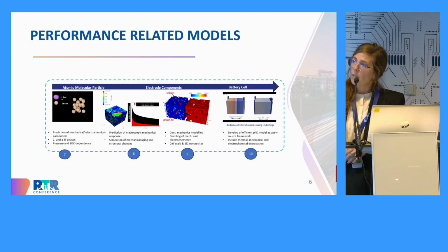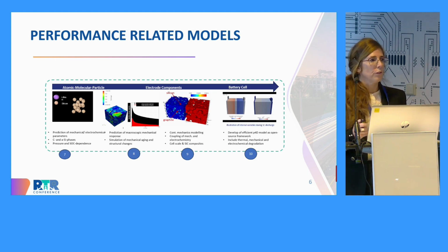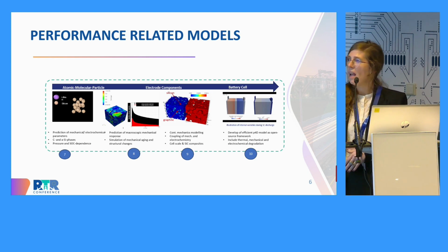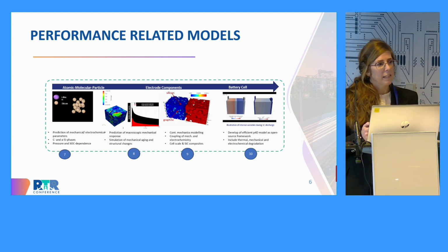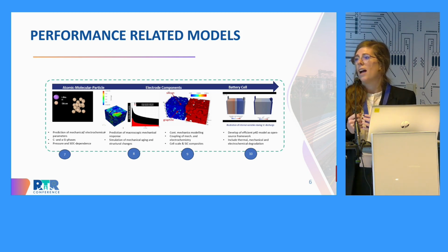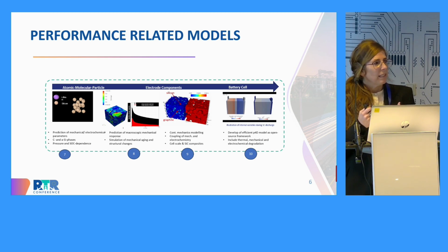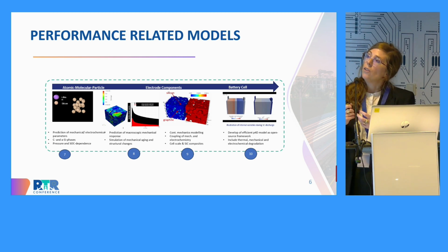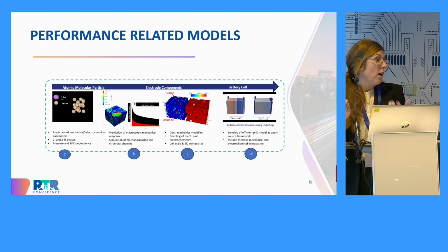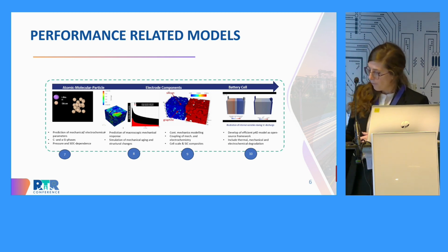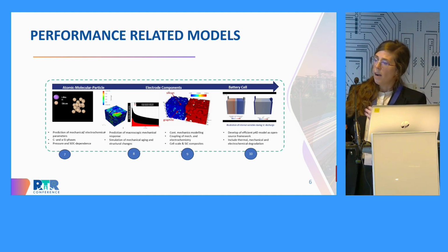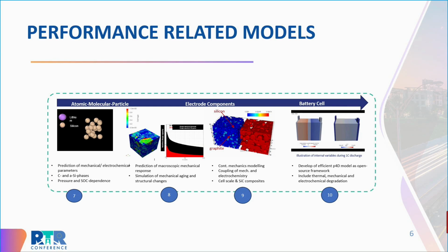So, and then now dealing with the performance, again with this multi-scale approach, we go from atomistic to meso to the continuous scale. And in particular in DEFACTO, we have this graphite silicon, and here it's really important to address correctly the swelling of the silicon, because otherwise it might cause certain cracking. And then this cracking will lead to higher polarizations, and also lower cycle life. So basically, from this multi-scale approach, we predict on the atomistic scale certain properties on the mechanical side, and give this information to the electro modeling, and then it turns to the battery cell, where you homogenize the information at the cell level, and then you can predict certain aspects of the whole cell.